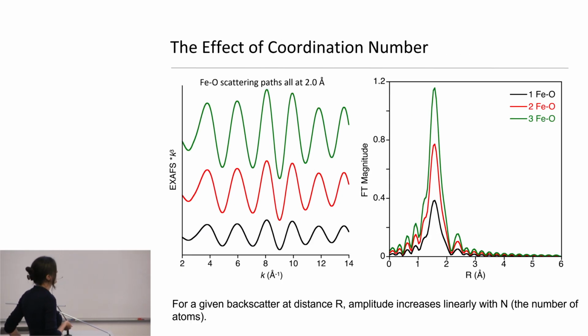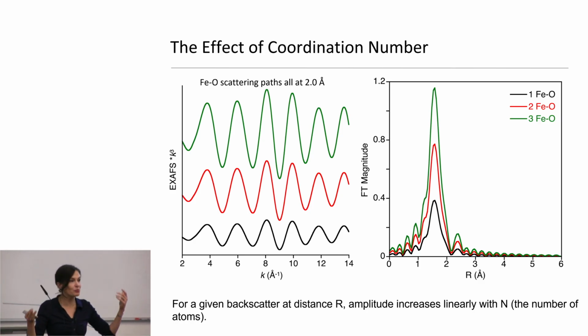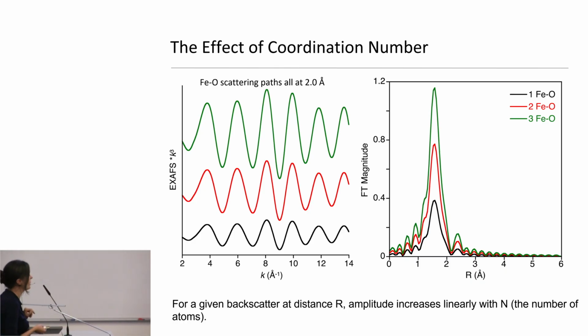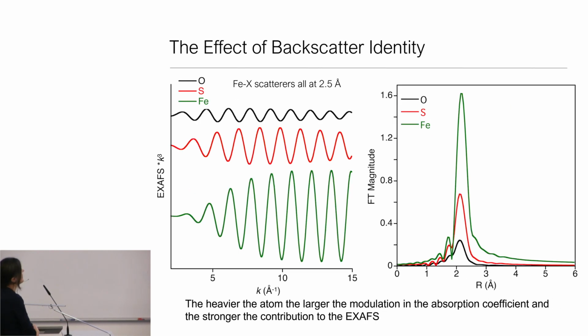And probably the easiest effect to see is coordination number. This was the linear n term at the front of our equation, so everything just goes up linearly in the XAFS and in the Fourier transform as expected. The very important part of XAFS, of course, is that the identity of the backscatterer actually matters. These are all iron scatterers, to the iron at a distance of 2.5 angstroms. And what you can see is that oxygen is a very light scatterer, so it has a weak amplitude, and it's weak in the Fourier transform. Whereas sulfur is a heavier scatterer, it's going to contribute more, and iron is the heaviest.